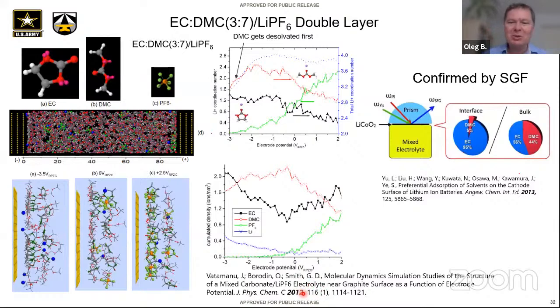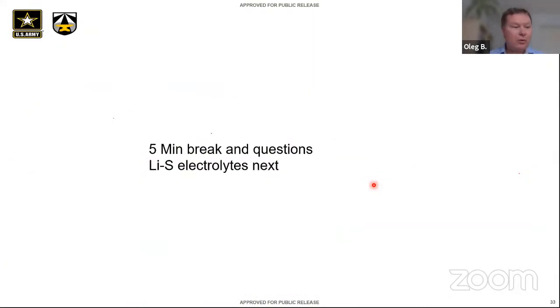I still like this result, especially because the next year a Japanese group reported sum frequency generation, where they said that while in bulk in this EC-DMC electrolyte there is a slight preference for EC, they observed, in good agreement with our results, that the interface is really preferred by EC compared to DMC, which is very consistent with this type of charged interface. Of course, there are other effects due to oxides and specific adsorption, but that at least gets at the positive electrode charge contribution, how it influences selectivity of species to be adsorbed at the interface and participate in reactions. Now we are done with this part, and it's a good time to ask questions.